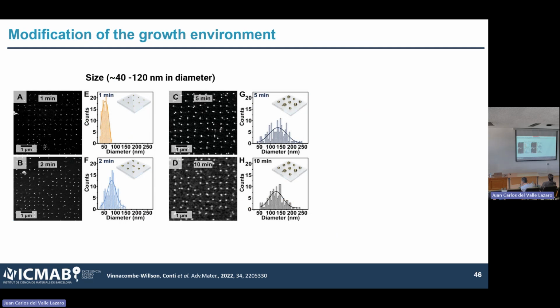So the first thing was, of course, let's grow it for different amounts of time. And so we saw that by growing it for less, by exposing our substrate for less time to the growth solution, we can go down to basically 50 nanometer. For those of you that have some experience with colloidal synthesis, we recently tried to change the pH of the solution. So we used acidic conditions. In those conditions, we were able to slow down the growth a little bit. And we were actually able to get this down to 20, 25 nanometer.